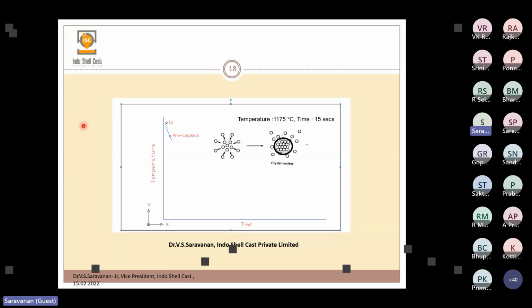But if you enlarge it at that particular time, if it is possible, because normally in the cooling curve software we cannot zoom it, but if you are able to zoom that particular point, you can see a small straight line, because there is a phase change only, there is no temperature increase. Like when you boil water, at the time it reaches 100 degrees centigrade, the boiling point, the temperature remains constant, and the water becomes steam. Like that, only the phase change is happening. So here a small phase change happens, because the metal will become a small solid phase.